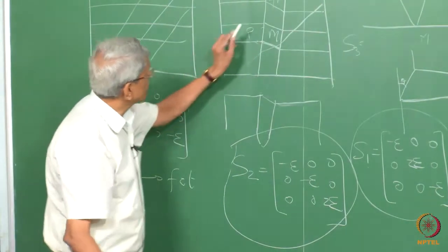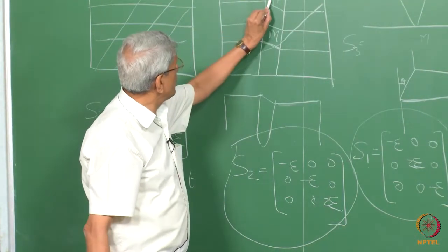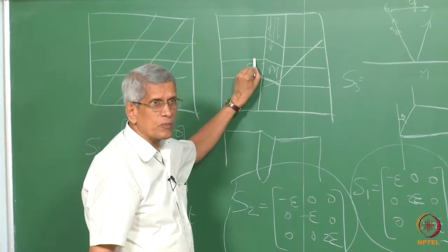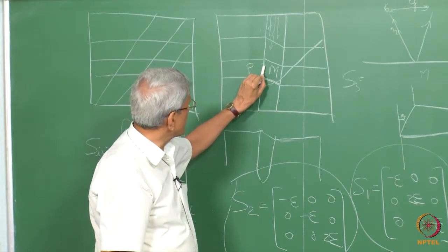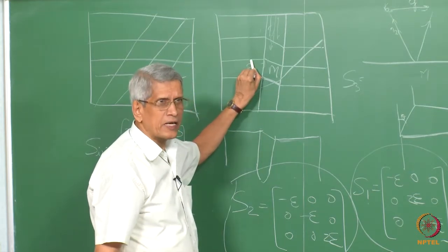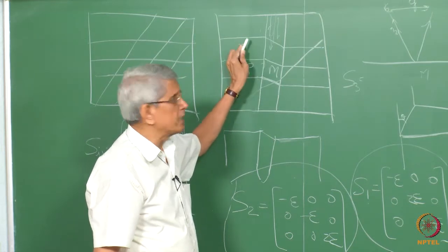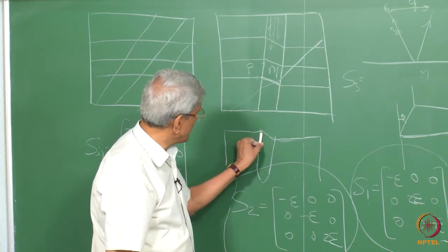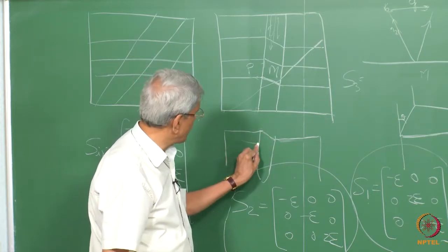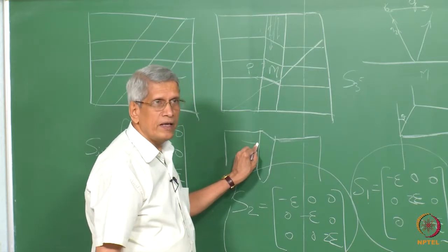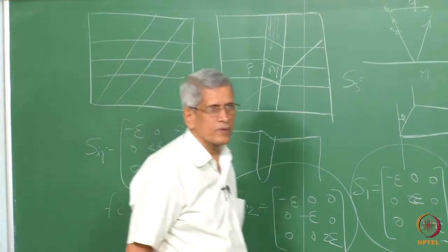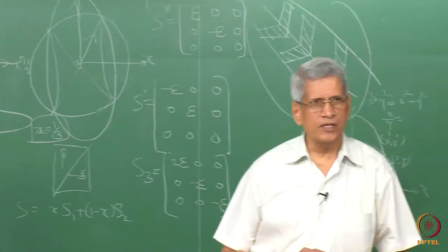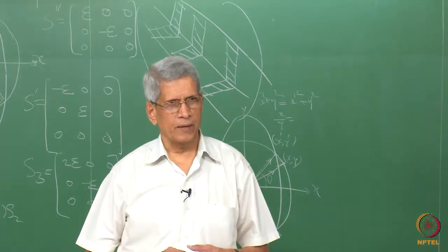So, when the martensite is introduced here with this macroscopic observable shear, the perfect matching is obtained here, but on the matrix side the effect is not being done. By rotating the crystal, that is, this surface relief which is coming, the strain is getting accommodated. So, on this side right up to the interface, there is absolutely no strain. This feature also this crystallographic theory is able to explain.